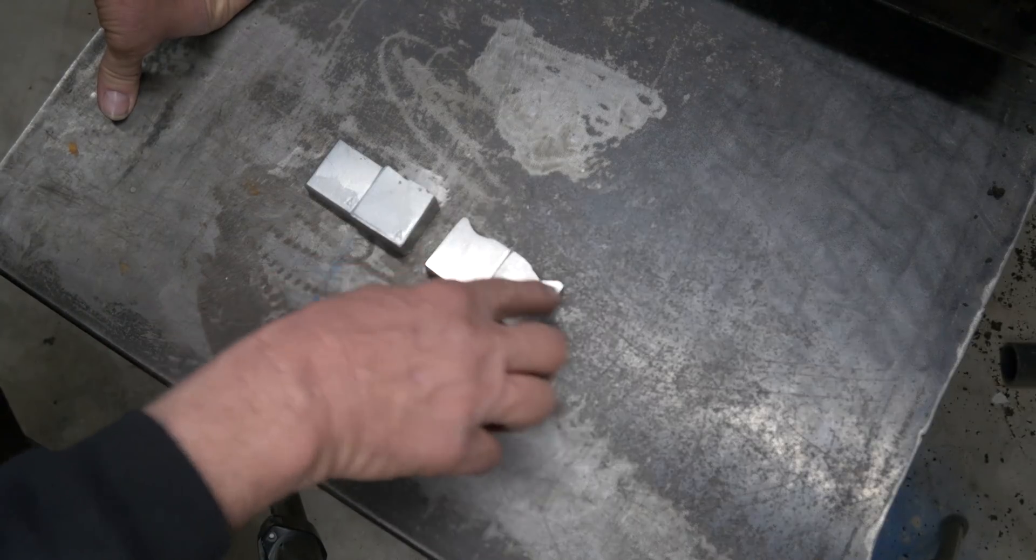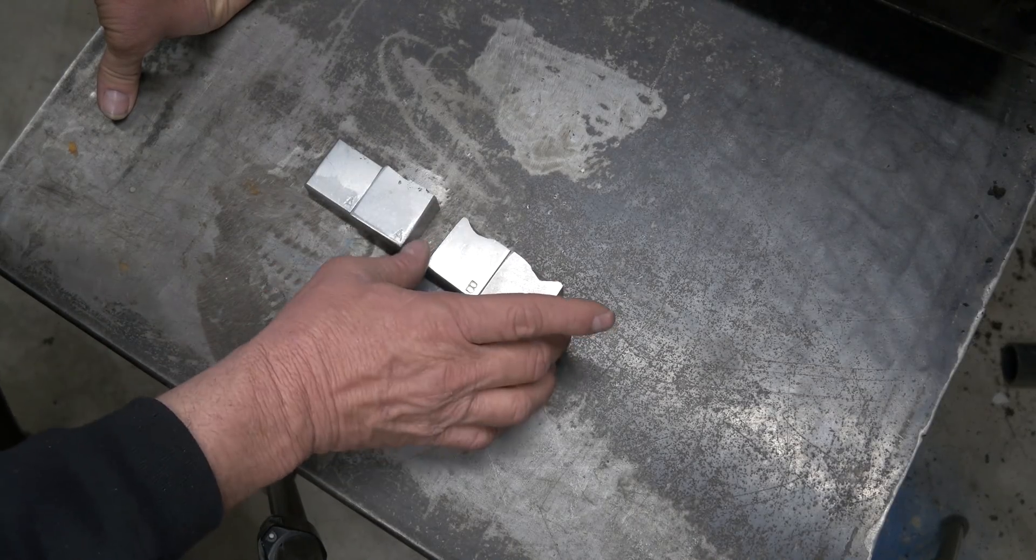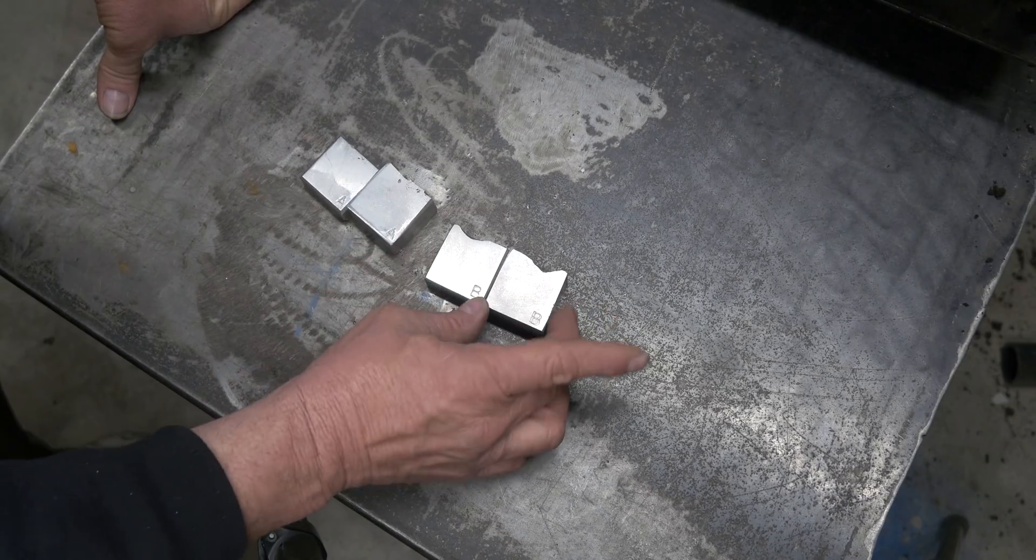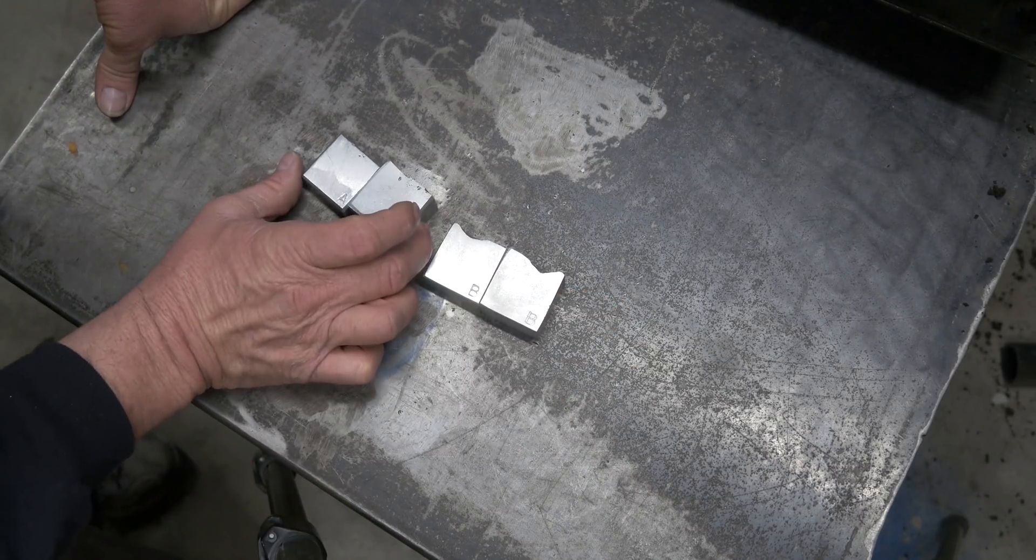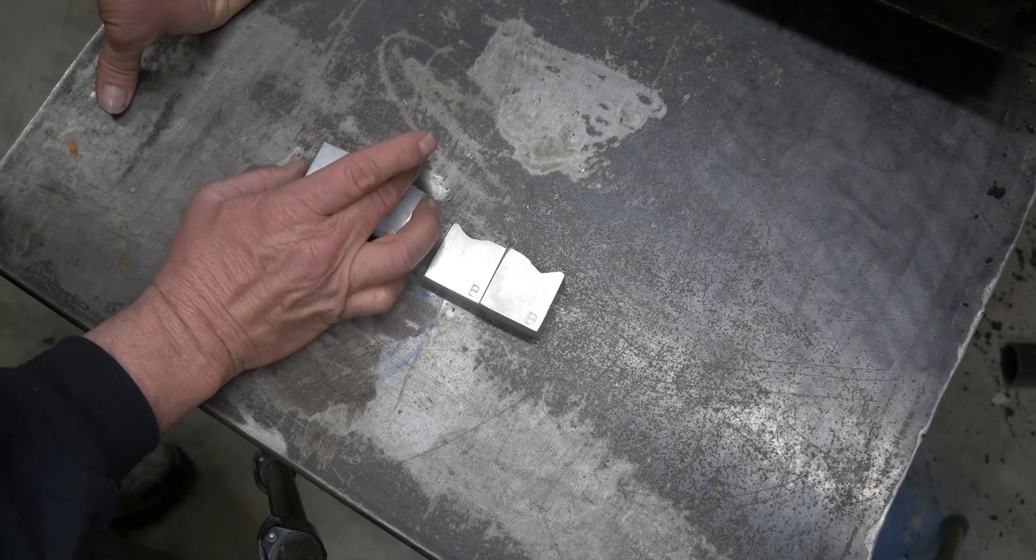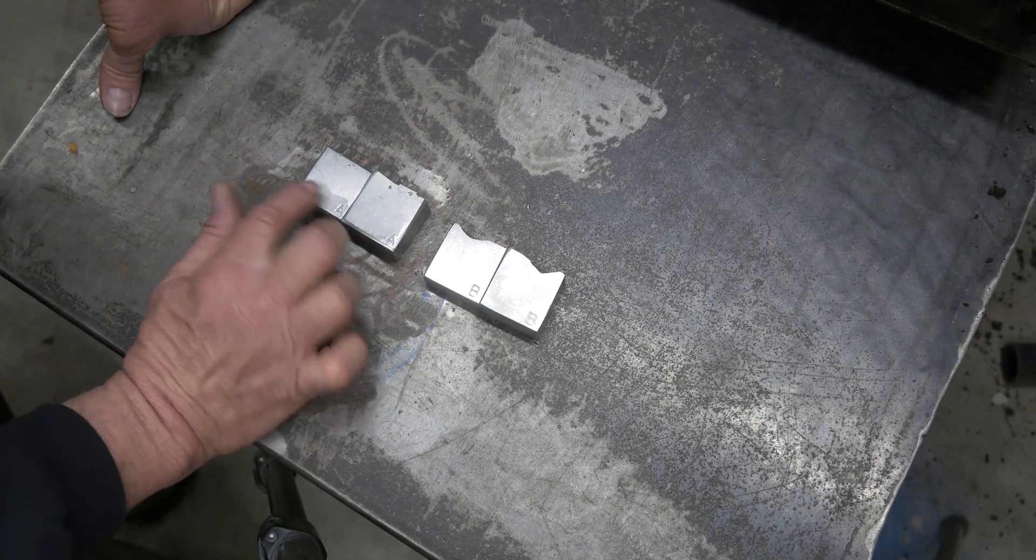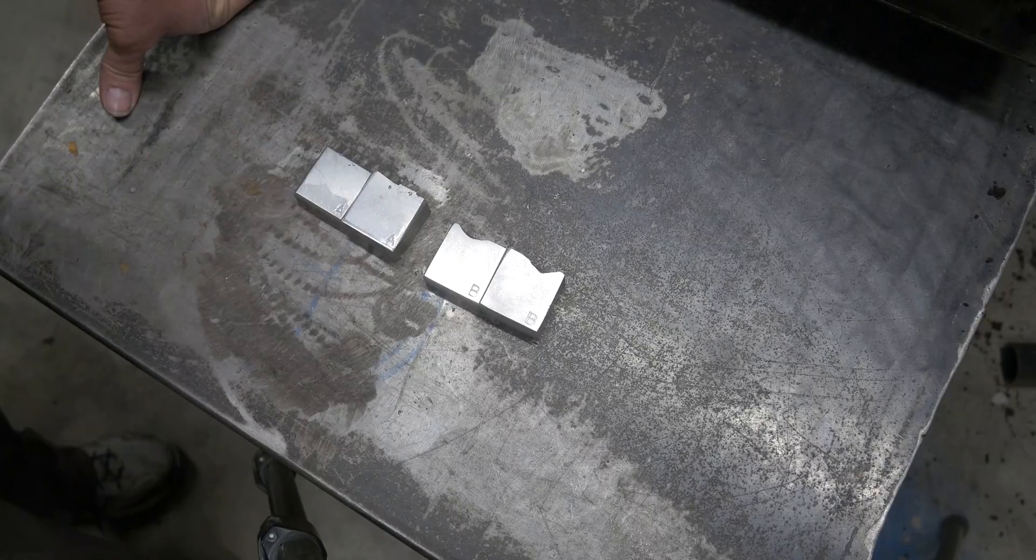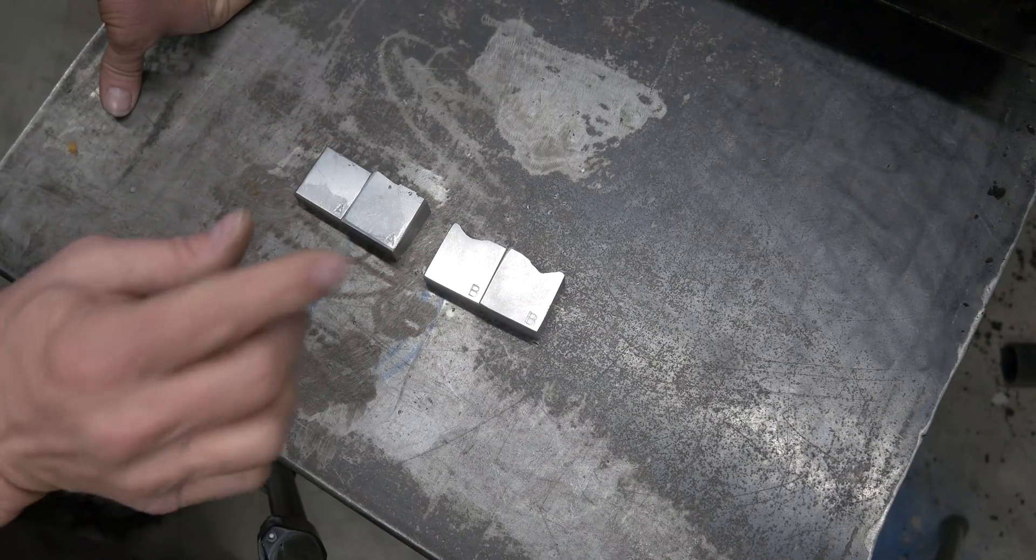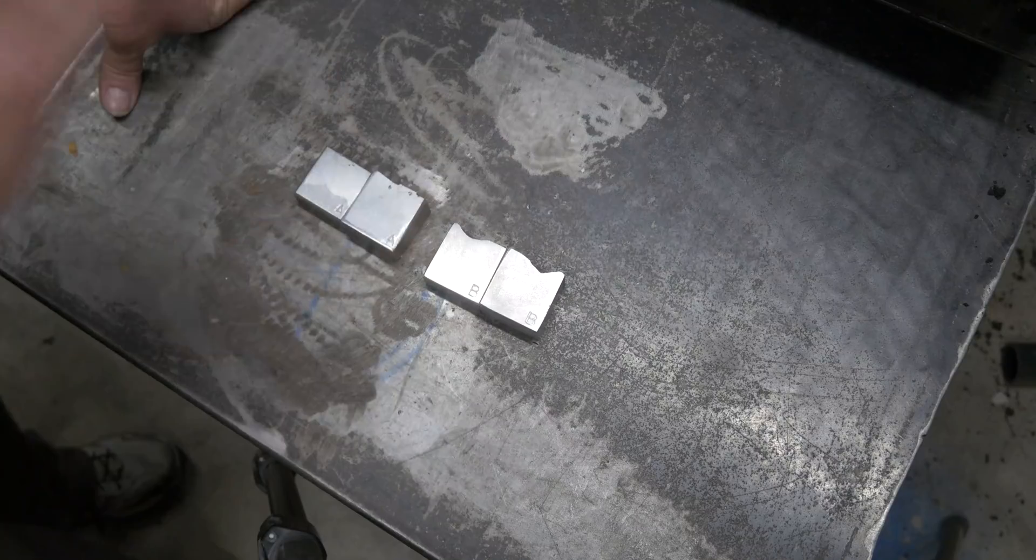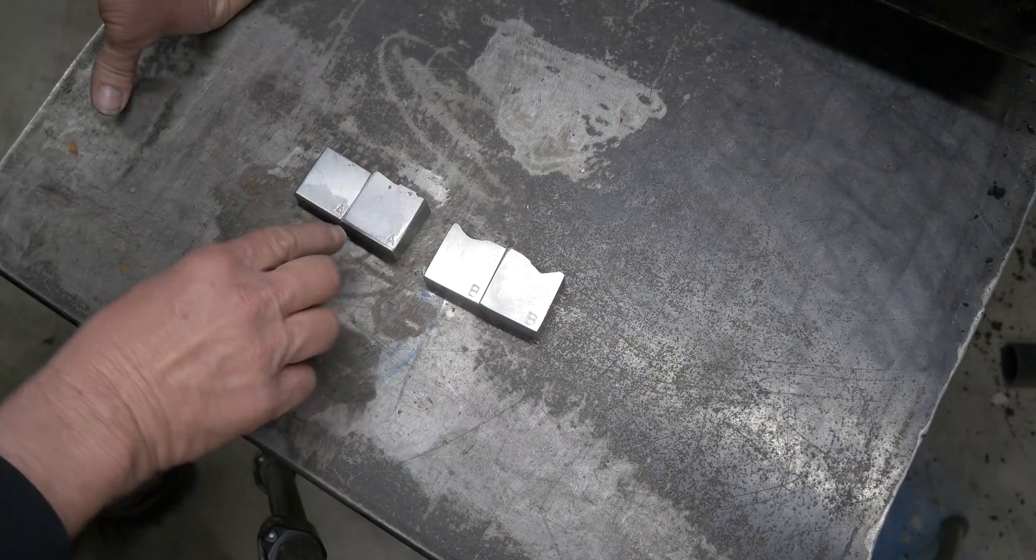Everybody noticed the shrink in the B. Again, the B block was using the small tapered sprue, the pouring basin, the fill from the bottom, vented at the top sort of thing. A is the one where we filled from a split mold, large open sprue, large runners, and we vented out the side.